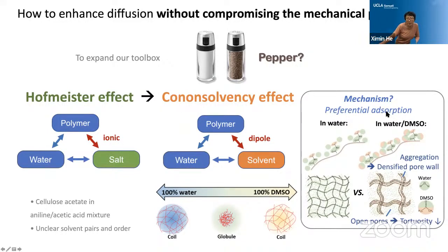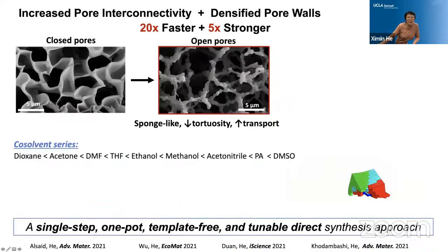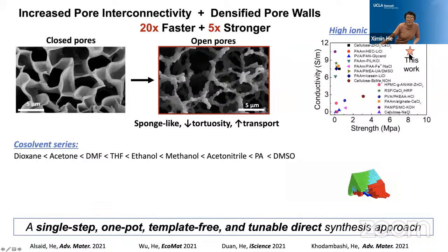So in the water-DMSO mixture at a certain ratio, we can achieve this nicely aggregated, densified pore wall, while leaving the pores in a more interconnected fashion. So it reduces the tortuosity. With this, we're able to increase the mass transport while maintaining the mechanical strength. So here you can see that we achieve improved ionic conductivity at the same time as high mechanical strength.